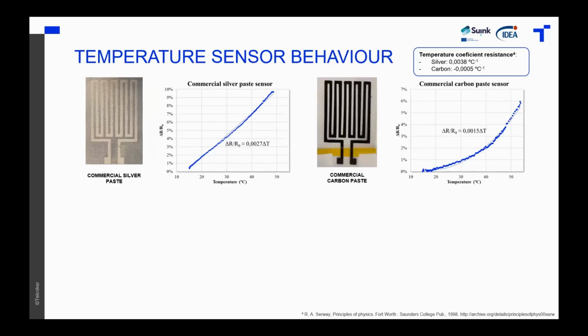On the other hand, we have the commercial carbon-based sensor, where we can see that the tendency is not as linear as the silver one, but we can approximate because the second order coefficient is small. It's true that the temperature coefficient of resistance of this sensor is positive, and the carbon ones found in literature is negative. But this could be explained because all the components that are in the ink are contributing to the temperature coefficient of resistance, so it could be possible.